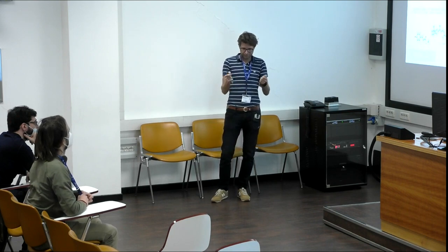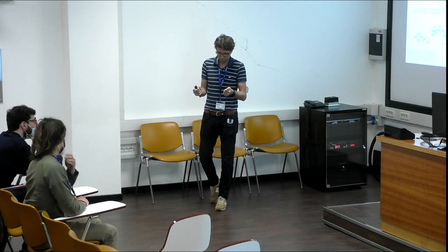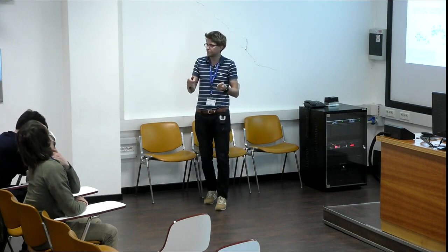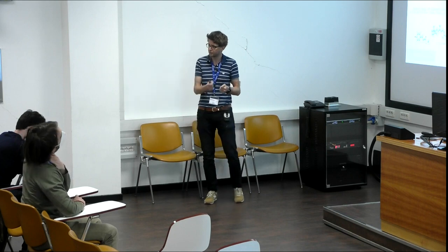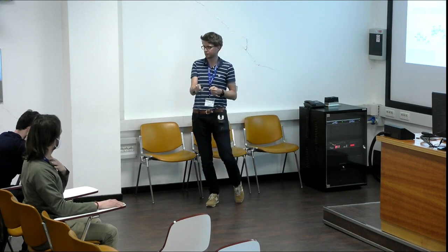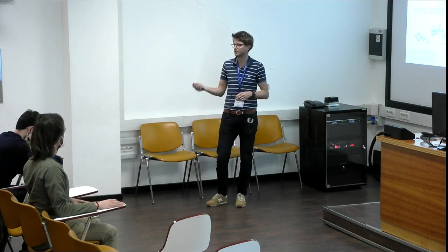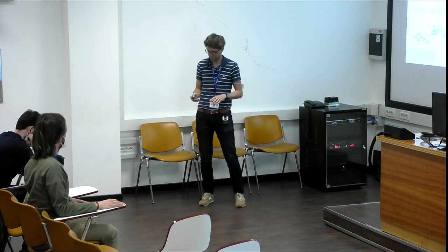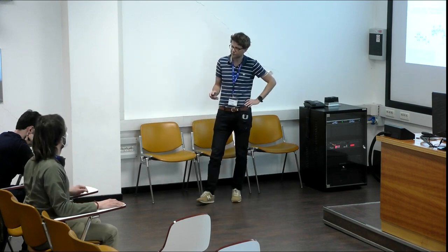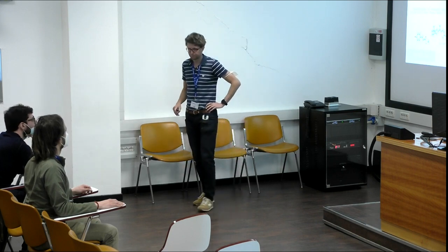And the other comment I have is that this balance is very tricky, and it has to do with the fact that the magnon, like the phonon, has to respect a sum rule. So you need to respect what is called Goldstone's sum rule. The magnon at zero momentum should be zero, at least without spin-orbit. And this is something you can check that it is respected by TD-DFT, by BSE at a certain level. And I would say that respecting this Goldstone sum rule is the most tricky part, because you need many bands. Thanks.